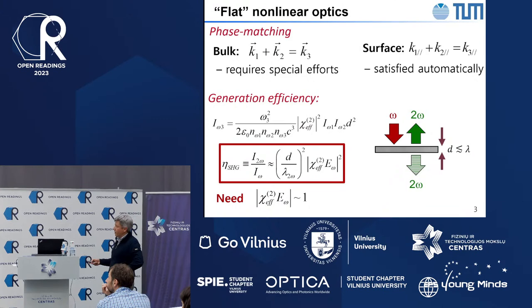So if you think about the generation efficiency of, let's say, sum frequency generation, the textbook expression is shown here, and you have the frequency of the output, the effective nonlinearity of the medium, and the product of two intensities. You can simplify this expression by, for example, assuming two frequencies are the same, and write an expression for what fraction of the input light is going to be converted to the nonlinear output. Then from this formula, you have a very simple expression by canceling some components of the order of one and expressing intensities through the electric field strengths, which tells you that if D is the thickness of the nonlinear metasurface, then the efficiency for second harmonic generation is going to be simply the ratio of thickness to the wavelength of light times this product.